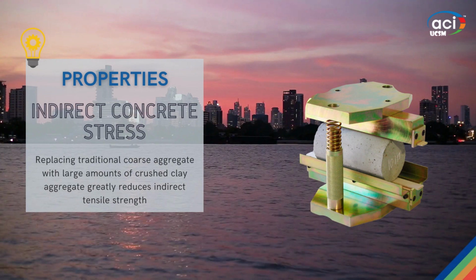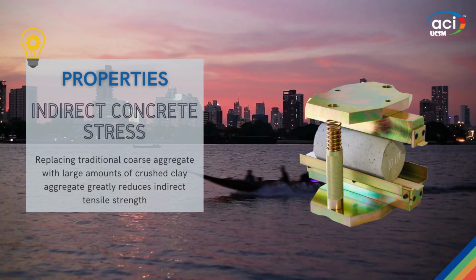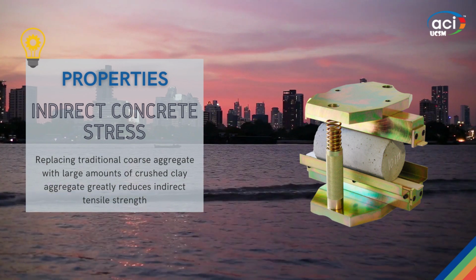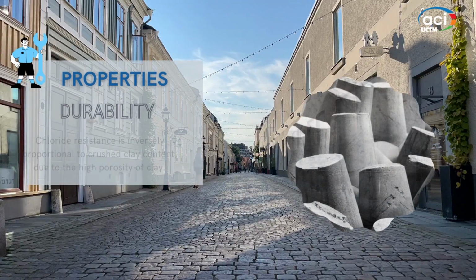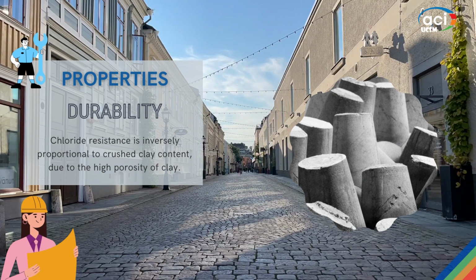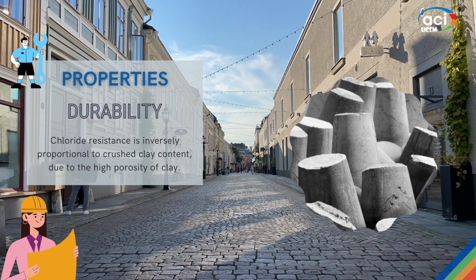Also keep in mind that replacing too much of the coarse aggregate with this material will reduce the tensile strength. The resistance to chlorides is inversely proportional to the content of crushed clay, due to the high porosity of the clay.